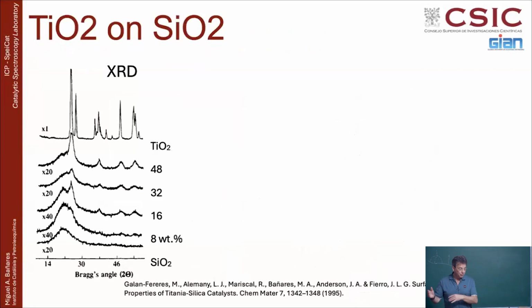You want to make a complete view and use different techniques. For instance, if you want to disperse titanium oxide on silica, you can do that. And if you look at the X-ray diffraction patterns, at the beginning silica will be amorphous. And then you put 8, 16, 32, 48 weight percent of titanium oxide on silica. And at the beginning you don't see that there is any titania, also because X-ray diffraction cannot tell crystalline domains which are smaller than 4 nanometers; they must be large enough to generate a diffraction pattern. Or if they're amorphous, there won't be a diffraction pattern. So at 16% you already see something, which is increasingly apparent as you increase, and here you have the reference for the titanium anatase. So basically you are starting to have a very incipient, very amorphous titanium oxide anatase.